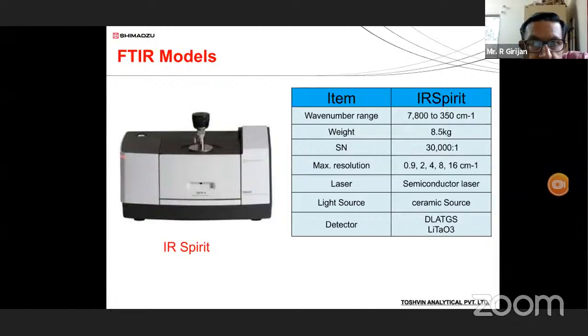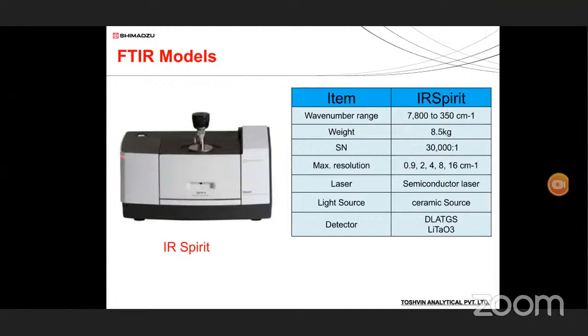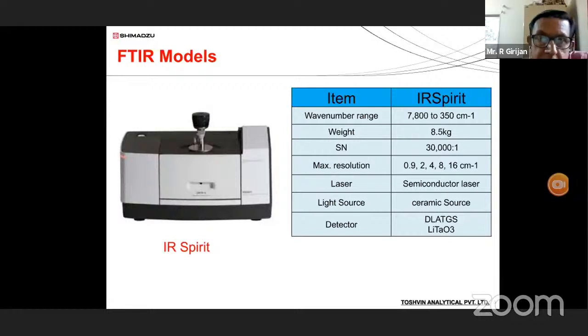Amol, I'll make a point here. Yes, sir. For the participants: for most powder samples, a resolution of 4 inverse centimeter is more than sufficient. A resolution of 2 or 1 is normally required only for gas samples. For normal liquid and powder samples, you get very satisfactory results with 4 inverse centimeter resolution, and that's why people use only 4 inverse centimeter for solid and liquid samples. Resolution of 1 or less is required only for gas samples. Yes, right.